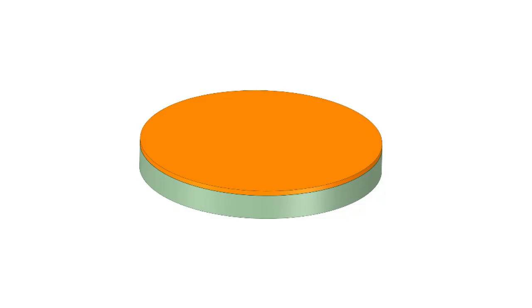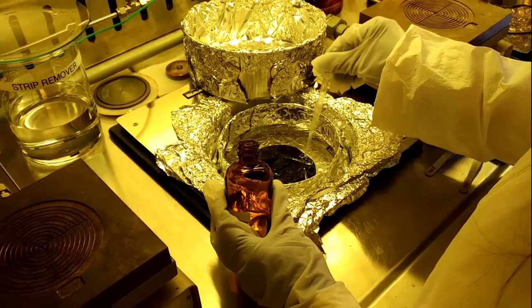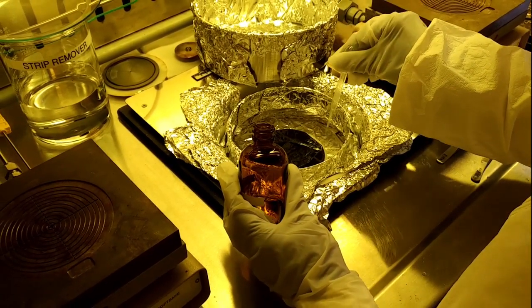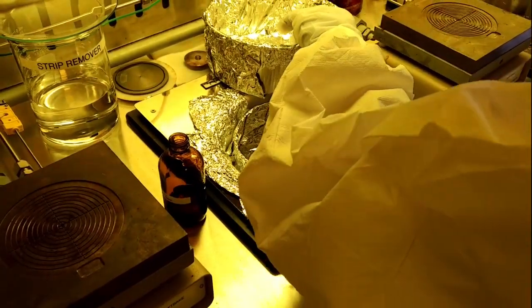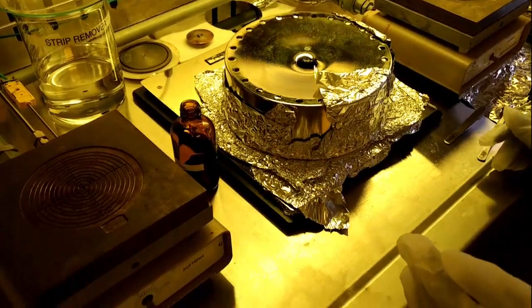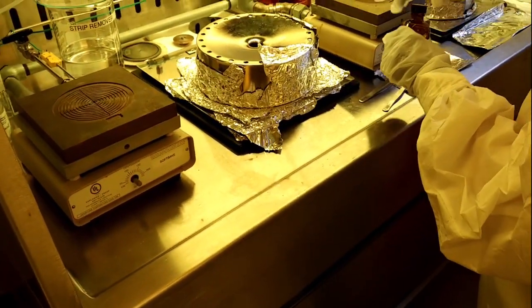Photolithography is used to add the patterns of photoresist to the wafer, which are required before the oxide layer can be etched. With the silicon wafer firmly mounted to the chuck of the spinner, hexamethyldisilazane, or HMDS, is first applied to the wafer. Once applied, the wafer is spun up to 5000 RPM to ensure a thin, uniform coating is left on the surface. The HMDS acts as an adhesion promoter for the photoresist, which will be applied in the next step.